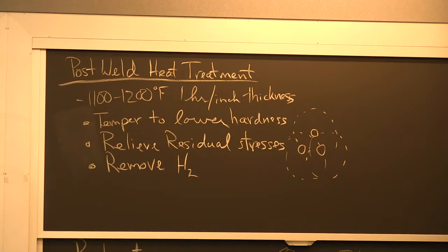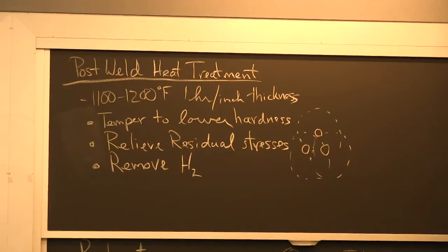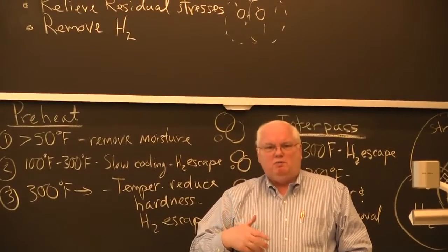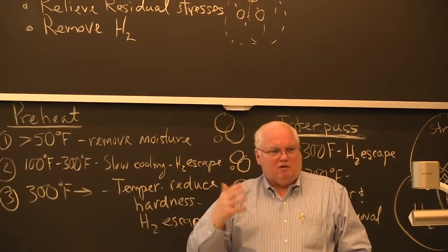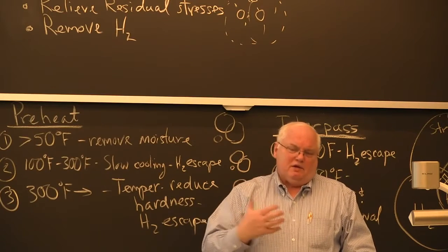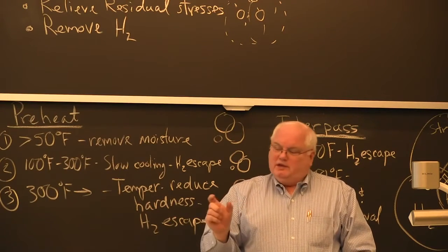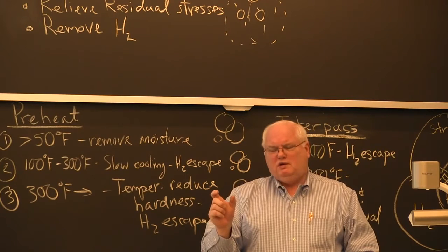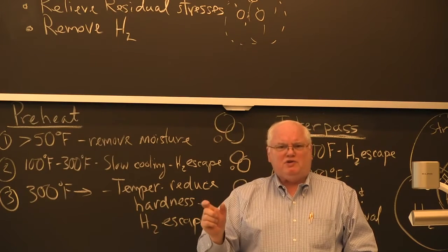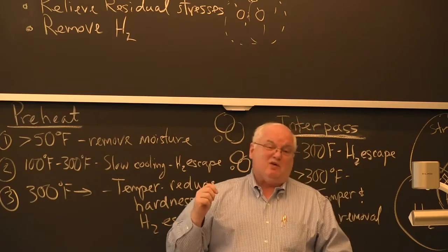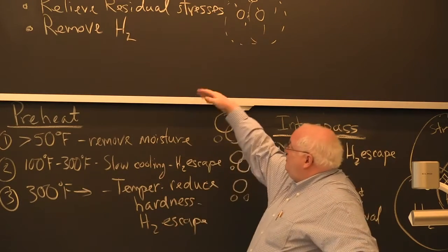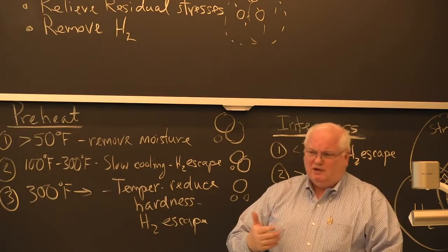I mean, if I put a roast beef in the oven, I might get it done on the outside, but the inside's still rare, okay? So you need about 1 hour per inch of thickness, with the thermal conductivity of steel, to allow it to heat up in the center. I want medium roast beef. I don't want rare roast beef. So the problem here is, for something between 1 and 3 inches, an hour per inch of thickness is about right. You start going to 10 or 12 inch thick steel, and it turns out you can sort of get away with a half hour per inch of thickness.